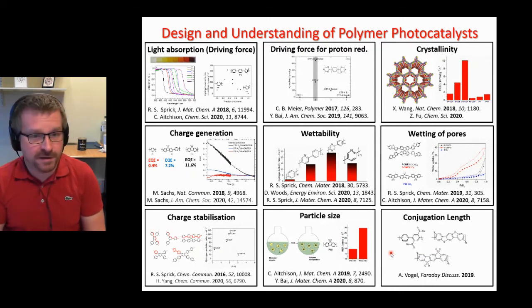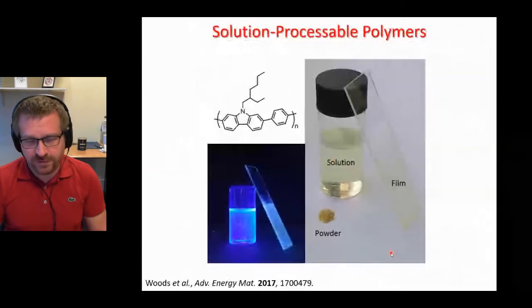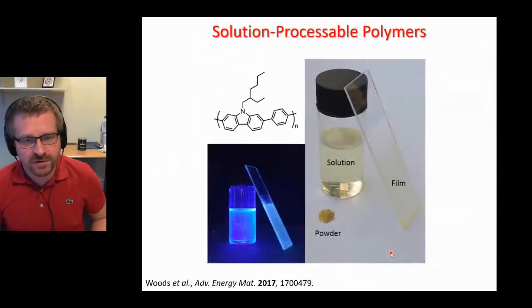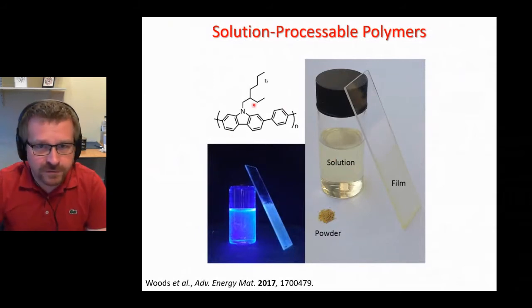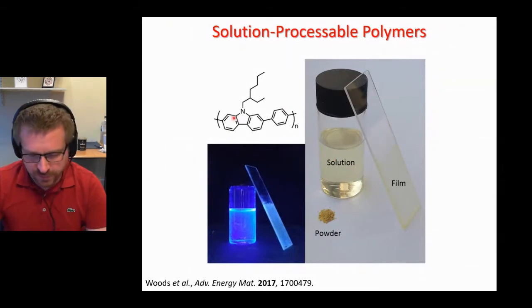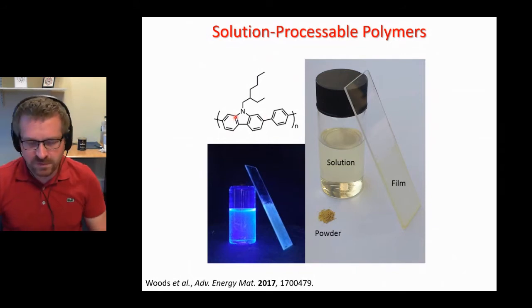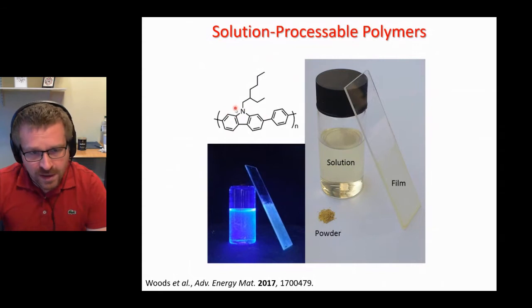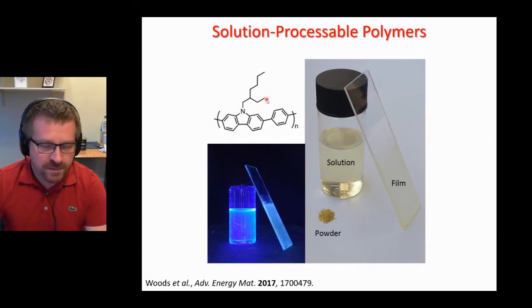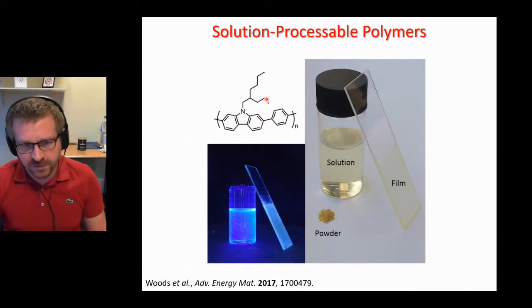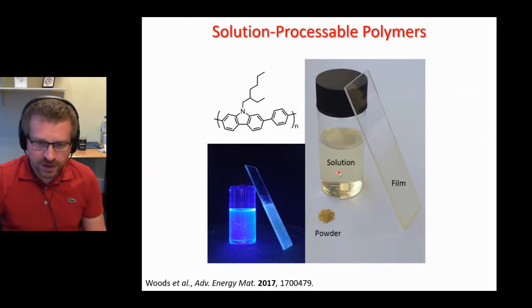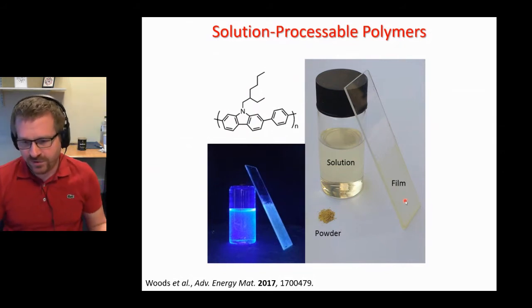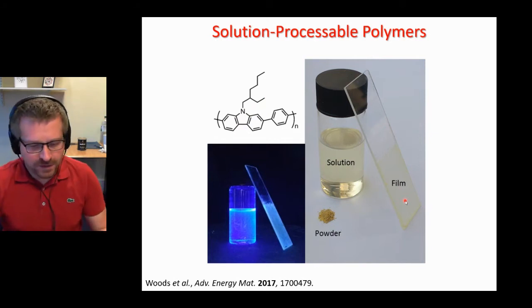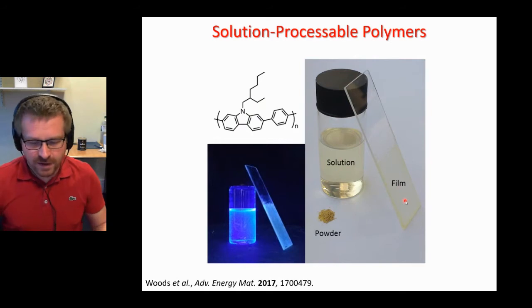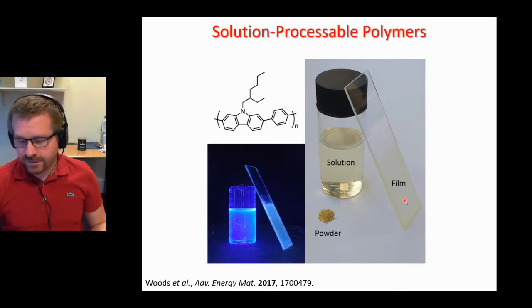It's really similar to inorganic systems as well. And that brought us to an area how we can distinguish ourselves from inorganic systems, and that is the area of solution processibility. All the materials on the previous slides were all insoluble materials, but we know in organic chemistry, if we include these side chains here, we can make materials that are able to dissolve in organic solvents. So we can make this material, and then we can dissolve it in a solvent. In this case here, it's chloroform, and then we can use that to cast films at low temperature. Really, it's room temperature, and that's an advantage for us compared to inorganic systems.